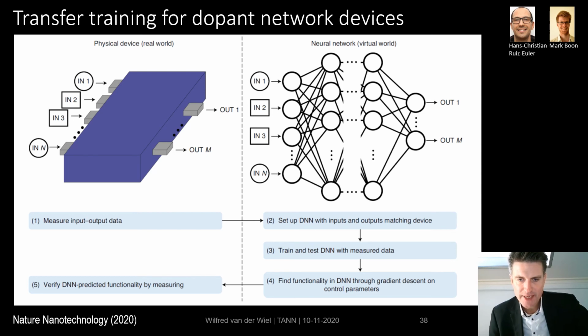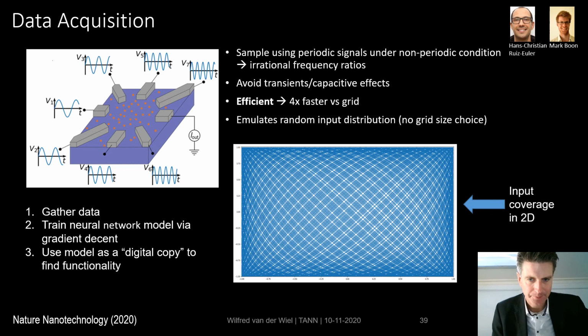The interesting thing is now that we can basically do this offline, so not directly on our physical device, but in the model, in a computer. We can use standard machine learning algorithms to find a solution for, let's say, an AND gate. Now, once we have found these values for the control parameters, we can go back to the physical device and apply these values that we have found in the deep neural network model to the physical device. And very nicely, we can see that this works neatly and that we can indeed measure in real life the desired functionality.